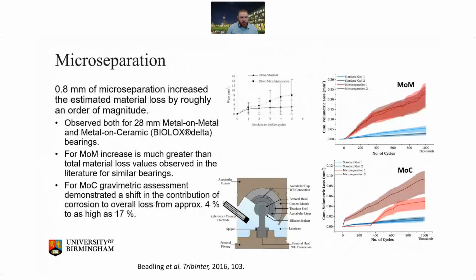So I took a look at the effects of microseparation, both for metal on metal and metal on ceramic devices. And what we noticed is, so these were specifically 28 millimeter bearing devices, and we had some existing data in the literature to compare to, which kind of showed a twofold, I think, increase in wear rate when you introduce microseparation. What we actually saw was an order of magnitude increase for metal on metal in the corrosive degradation, or the estimated material degradation, material loss as a result of corrosion from that bearing surface.